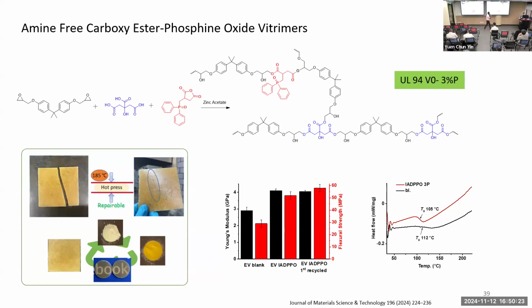Okay, so this chemistry is also quite recyclable. You can see you can break it and repair it as many times. You have very high mechanical performance even after a few times of recycling, I would say. And the glass transition temperature is also quite high for this system. So it's another chemistry where phosphorus is not directly linked to the network. It is on the side, I would say.